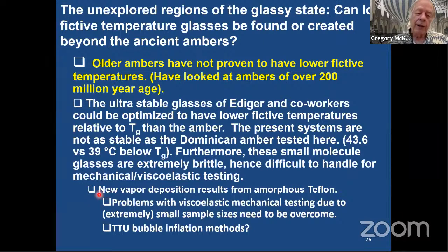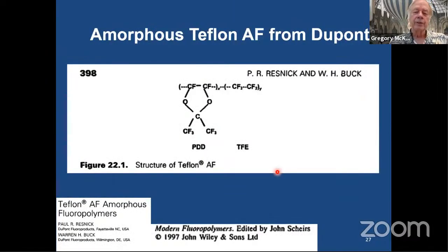So we figured out a way to vapor deposit an amorphous Teflon, and we met the challenge of when you do vapor deposition, you get micrograms of material. We met the challenge of measuring the mechanical properties by using the Texas Tech bubble inflation method that we had invented some time ago for studying ultra thin films. So here's Teflon. That's the amorphous Teflon. So it's important it doesn't crystallize because we want it to be easy to handle with the glass without worrying about crystallization issues.